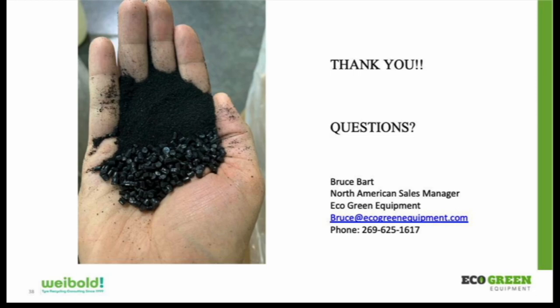Absolutely. Going through basically the same process of grinding. And when I say grinding, not in our equipment, in the plastic processors' equipment. So the plastic processors that are using general granulators with whatever size screen they're using, 1/8 inch, 1/4 inch, 3/8 inch, they're able to do the same thing. It's just important to note that, as they introduce the materials into their process, they need to know what the rubber content is.